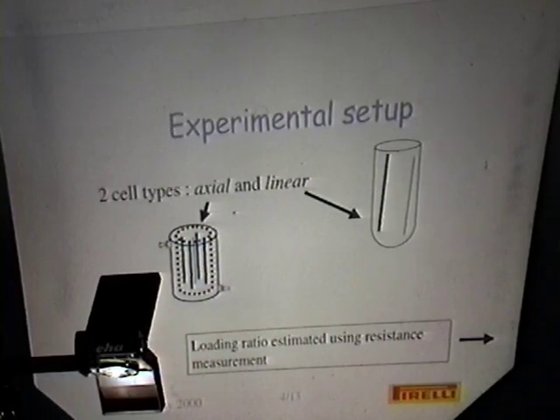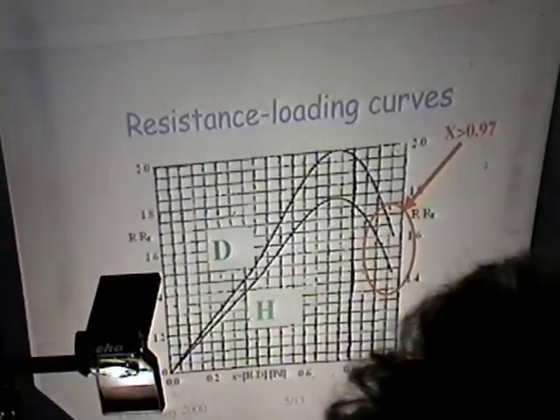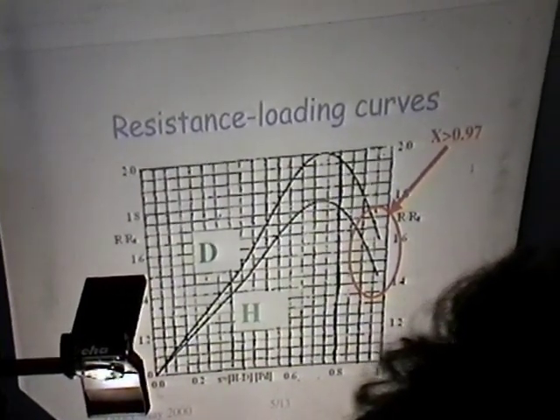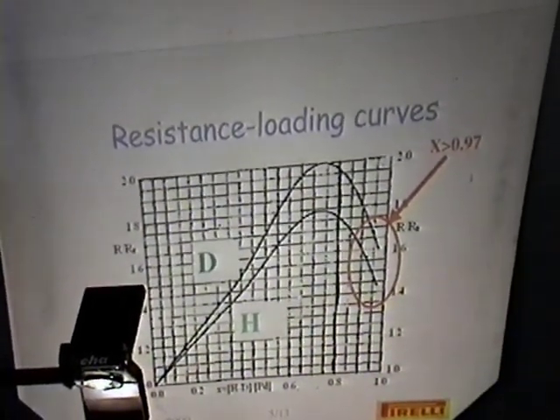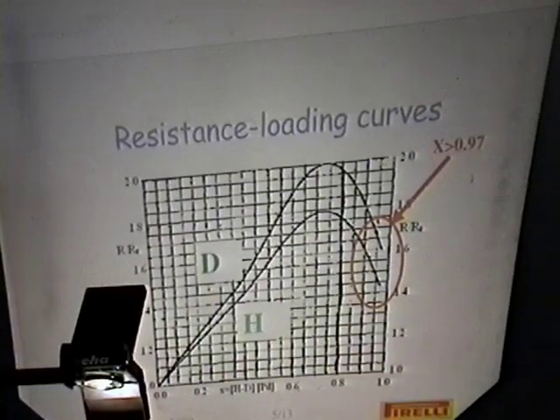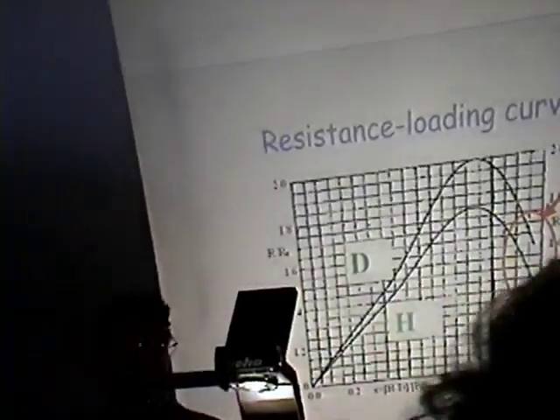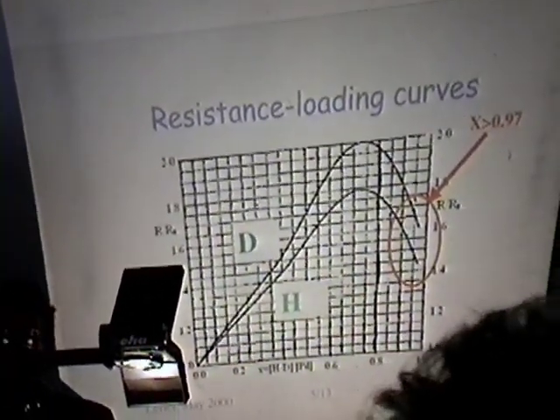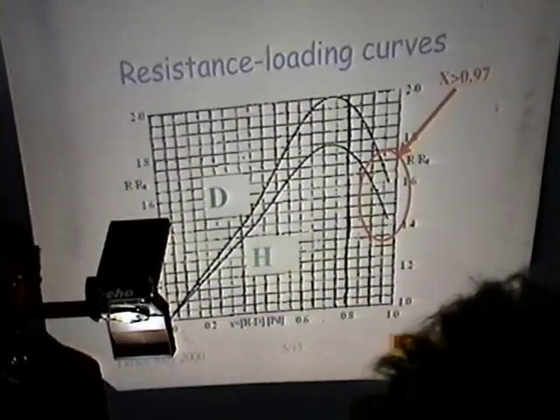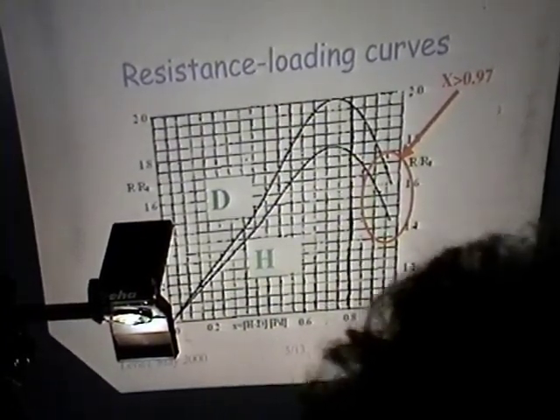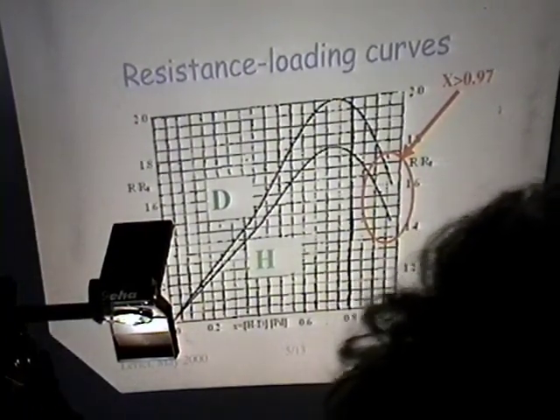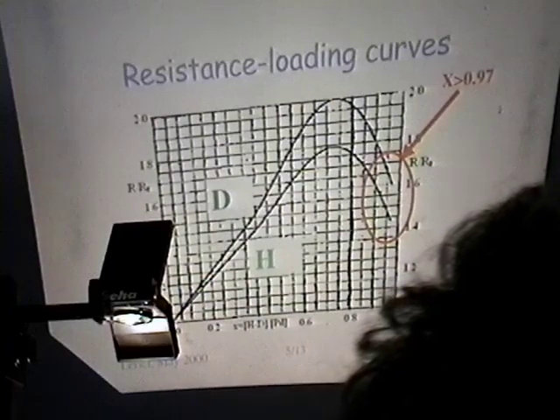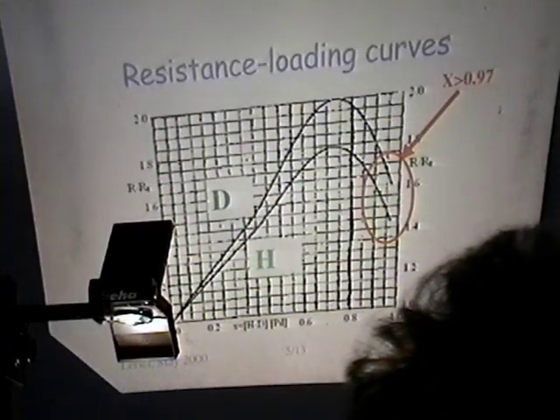The use of thin wire was explained in a lot of talks. It's because in order to measure the loading, we use this famous curve, and so we can estimate the loading via measurement of the resistance of the wire. We are interested in exploring the zone that I emphasized here. In particular, for hydrogen, the curve limits to the value 1.43, and we have overcome this value. For deuterium, the limit is 1.6, and this is almost the limit value we have reached.